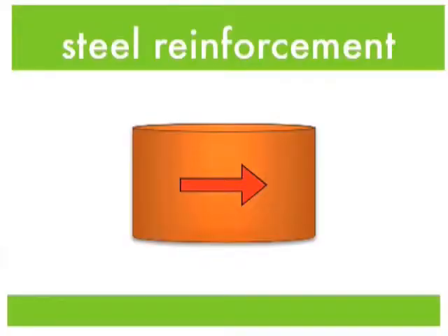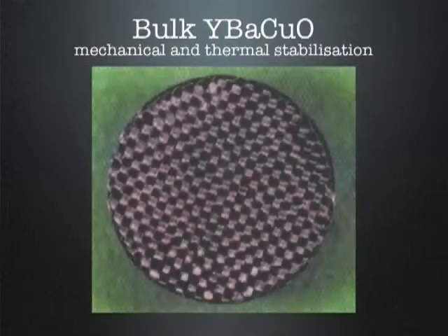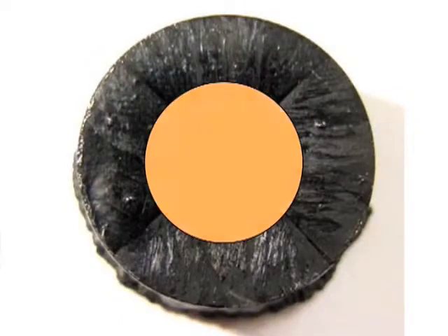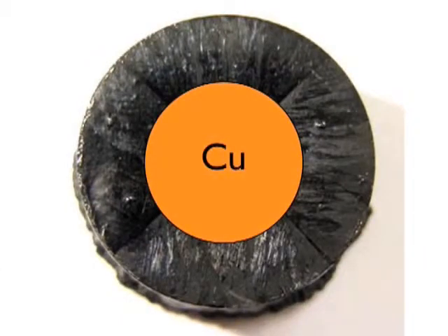Now the problem there is that the forces on these samples are enormous. So you have to reinforce the materials, and you can do that either by steel banding, so you put a steel band around and you have a hoop stress that resists the explosive stress on the superconductor, or you can encapsulate in carbon fiber resin, or you can drill a hole down the middle and put a good thermal conductor there. So if there's any instability, then you get rid of heat very efficiently and you don't lose superconductivity.